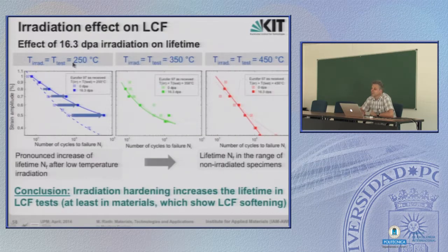Let's first restrict ourselves to the lower temperature, where the material embrittles most and where it shows the most hardening. And funny enough, the lifetime is increased, and it is increased enormously. We have a really pronounced increase of the lifetime after low temperature irradiation. And again, that's the beneficial or positive effect of hardening. This is what we have said for cyclic loading. There are many defects, and these increase the lifetime. If we go to higher temperature, then hardening vanishes and there is almost no difference between irradiated and unirradiated. Of course, this is only true for, again, 9% chromium steel here. So in conclusion, irradiation hardening can increase the lifetime in low cycle fatigue tests.